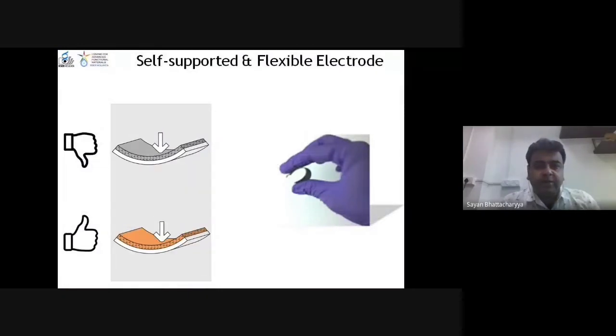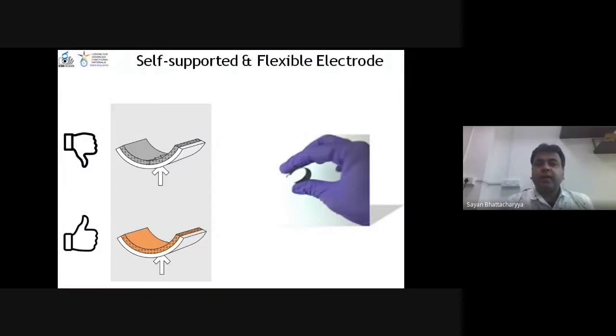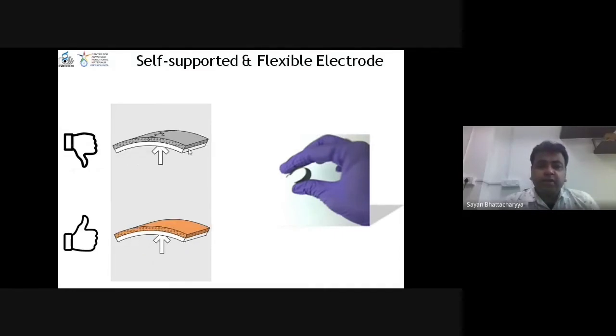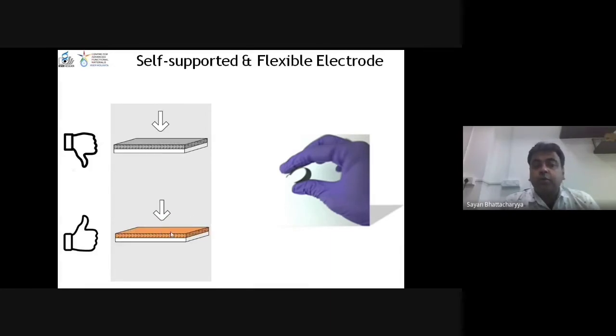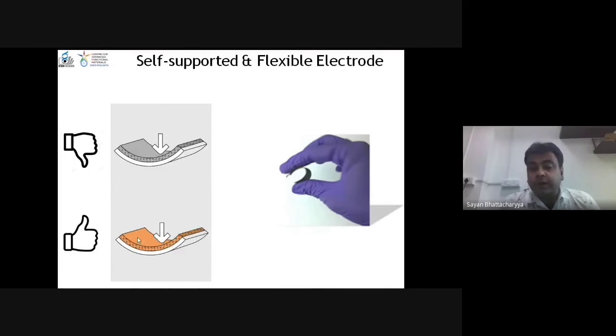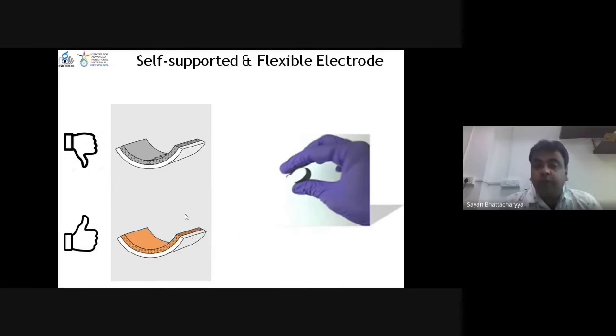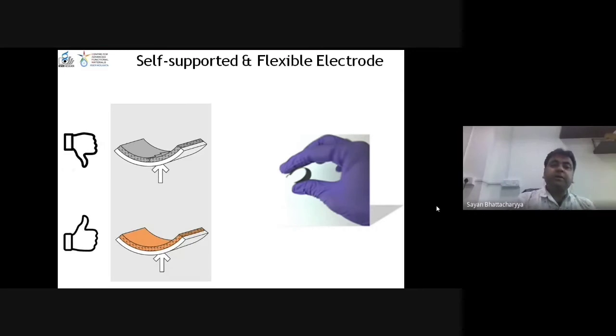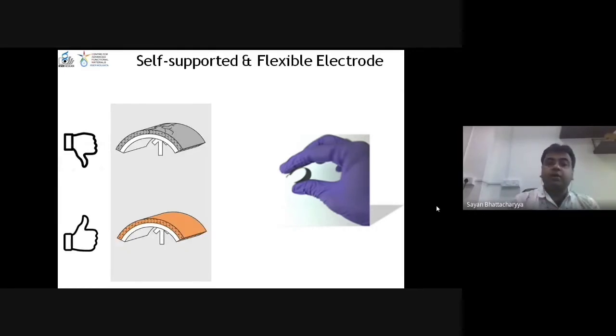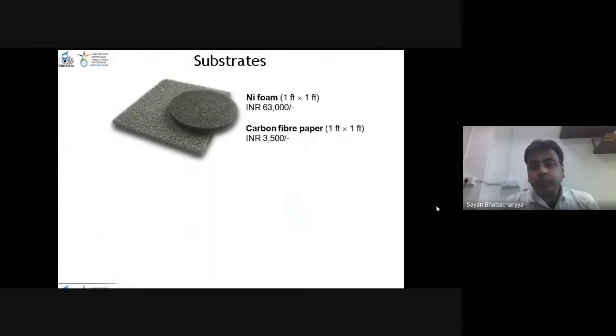Now, first thing I'll tell you about the self-supported and flexible electrode. You see these two, these are the substrates. If you bend up and down, you see the cracks on the surface, which is not a good thing. Here, if you do this, you do not see the cracks. So this is better. And this can only happen if you have a flexible substrate, because it has to sustain this energy conversion for a long time.